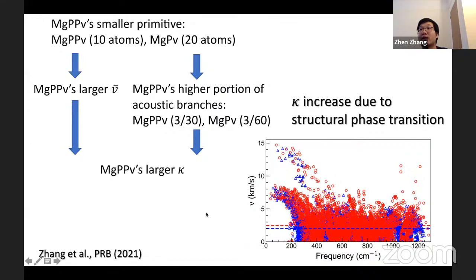More importantly, the major contribution to the thermal conductivity is from the three acoustic branches, with large phonon velocities and long phonon lifetimes among all phonon branches. The proportion of acoustic branches for post-perovskite is 3 out of 30, but for perovskite, this proportion is 3 out of 60. So when summing and averaging over all phonon modes, magnesium post-perovskite's higher proportion of acoustic branches also leads to its higher kappa. Therefore, there is a kappa increase due to the structural phase transition from magnesium perovskite to magnesium post-perovskite.